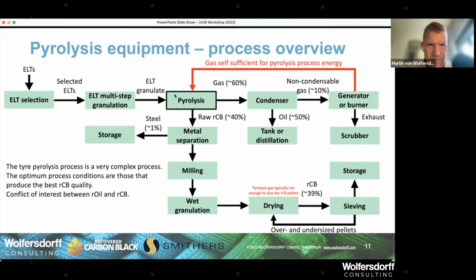One question, Vikrant Naik, do impurities or ash also come in because of use in field and on roads? Yes, of course, the end-of-life tires, you will have the debris in the tread still. And if you want to have a good recovered carbon black, again, that debris should be cleaned. And the best stage would be after granulation. Most of the continuous processes and even many of the batch processes don't use the whole tire, but have a shred or granule feed. At that point, it would be good to get rid of the road debris.